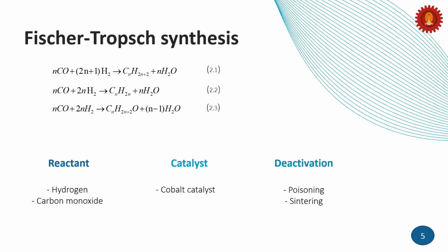Cobalt-based catalysts are of particular interest for industrial application due to high activity at low temperature, high selectivity toward long-chain hydrocarbons, and a long lifetime. A lower deactivation rate is usually found using cobalt catalyst under pure synthesis gas, but cobalt is more sensitive to impurity, and deactivation of catalyst in this research focuses on sintering and poisoning.